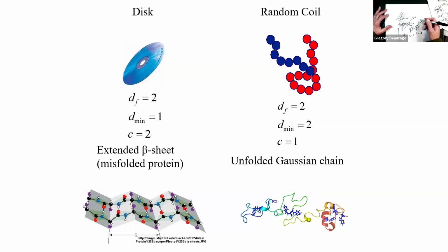So if you could do scattering on that, I by C versus Q on a log plot, you see it's one dimensional. You get a -1 slope, that would be the 1 over the R size. And then all of a sudden it would go to 2, and that would be 1 over the squiggly thing size. And then again, if it was fibers, it would go back to 1 when you got to the Kuhn.